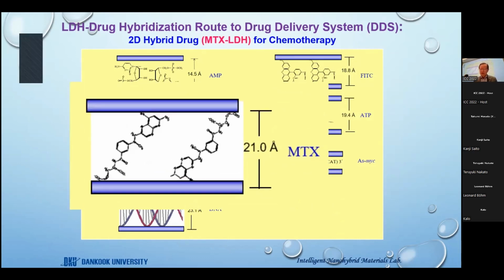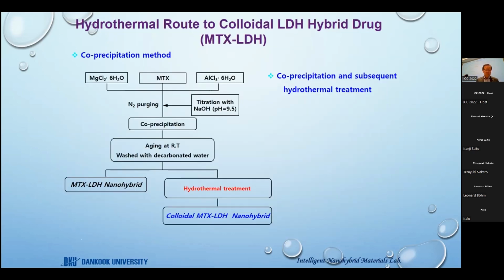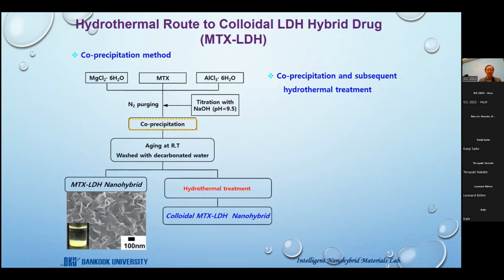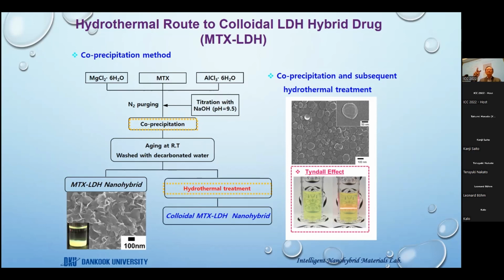So now we decided to develop a chemically well-defined MTX LDH nanohybrid drug delivery system to overcome such drawbacks of MTX, such as a very short plasma half-life and drug resistance. Well, let me tell you how we prepared the colloidal MTX LDH nanohybrid structure. First, LDH was prepared by the simple co-precipitation method, and the thus prepared precipitate was further hydrothermally treated to obtain a colloidal drug by controlling the hydrothermal condition, such as reaction temperature and time.